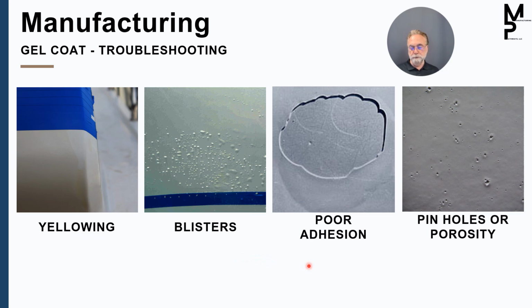Okay, if I'm too late getting onto the laminate, I might not stick to the laminate, in which case I'm going to have a breakout like this where the gel coat did not stick to the subsequent layer. Here's a good example of porosity where air got whipped into the gel coat, and now it's on my part, and I've got porosity. I got a lot of rework to do to get that looking nice.